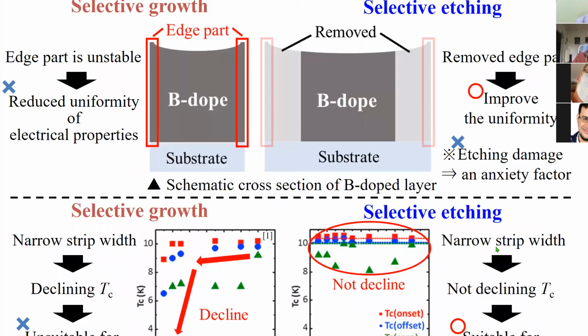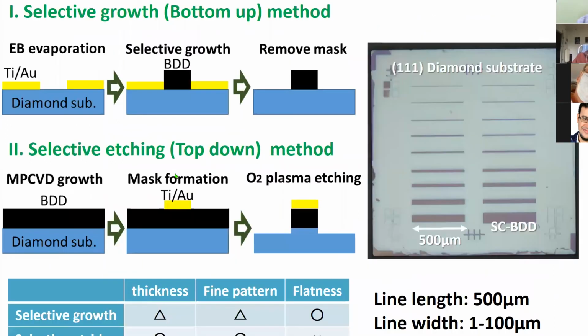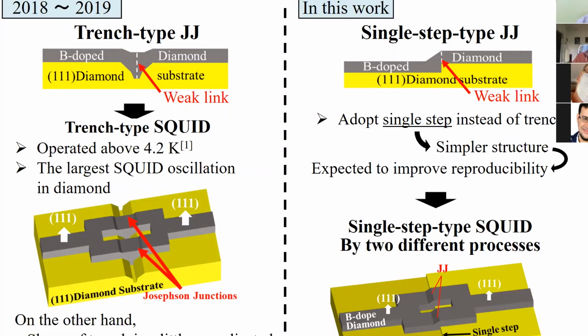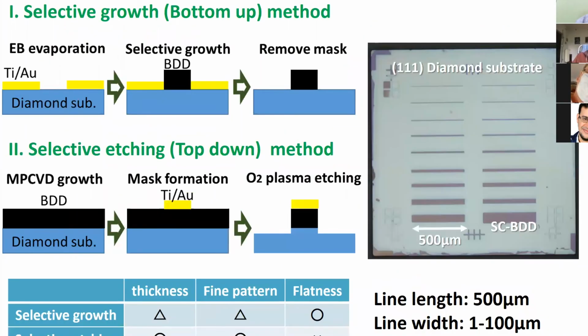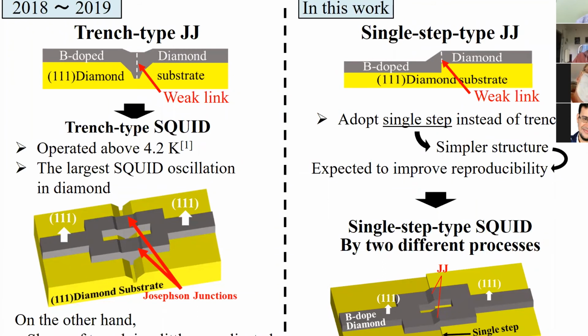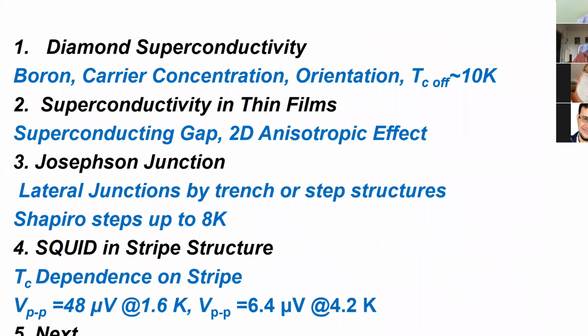Also, what we want to get is small lines of the boron-doped layers to get a small junction. This is a relatively large junction that we obtained - this is 30 microns, so that's what we showed before, I think. Okay.